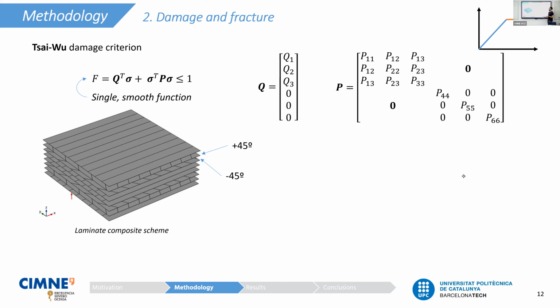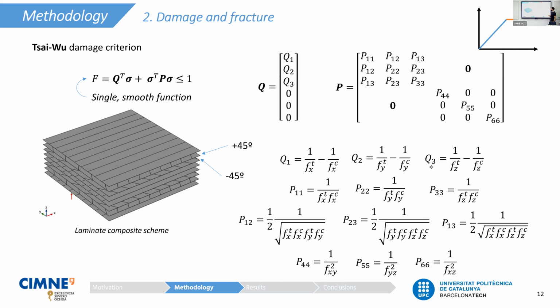This Tsai-Wu criterion computes a stress factor F that is computed using a linear and a quadratic term, and this stress factor is normalized, and therefore it has to be less than or equal to 1. If it's higher than 1, it means that the material is damaging. It is going into the nonlinear regime. The array Q and the matrix P are basically based on the material strengths of the material, which are characterized in this way.